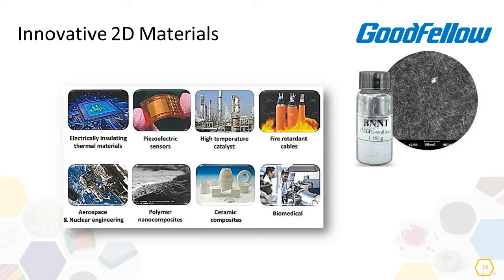For example, boron nitride nanotubes can be used as filler in polymers such as PMMA, polymethyl methacrylate, PS, polystyrene, or polybutylene as well, enhancing the heat dissipation capacity while maintaining their electrical insulation. These composite materials can be used in IT devices, such as in PCBs. Due to their high surface area, they can be used in catalysis for removal of environmentally hazardous elements. For example, the conversion rate of carbon monoxide can be higher in a catalytic converter of the exhaust.